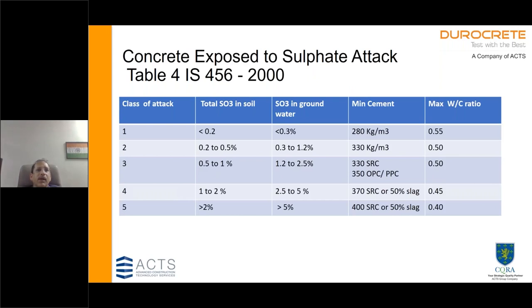Now this is Table 4, given in IS 456, that is very very often overlooked. So when you do a soil investigation report, you generally test for every meter. Apart from the index properties, you are also checking for sulfates and chlorides. Okay, so the code has already defined the minimum cement content and maximum water cement ratio for different classes of attack, and they have defined these classes of attack.